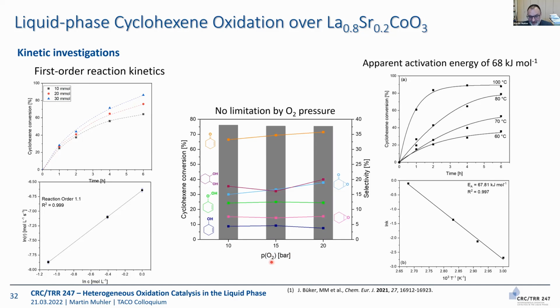Then you have to check, are you limited by the oxygen pressure? You pressurize more and more, but you see that there's hardly any influence on selectivity. You vary temperature and, just making simple Arrhenius plots, you can derive apparent activation energies for that catalyst. And the products you get, you see it's mainly the ketone, also some of the diol, and the hydroperoxide, that is this intermediate that has to be decomposed. And actually for the decomposition of this hydroperoxide, you also need the cobalt 2+ ions that you get by substituting strontium into it. And to some extent, you also get the alcohol and some epoxide.